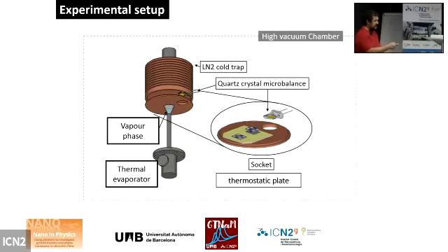We have a plate controlling temperature within a few millikelvin, typically with a set of high resolution sources and SMUs, giving control around 1, 2, 3 millikelvin. The material is evaporated from a thermal evaporator, arrives in vapor phase, and we can monitor with a quartz crystal monitor the amount of material that is arriving to the system.